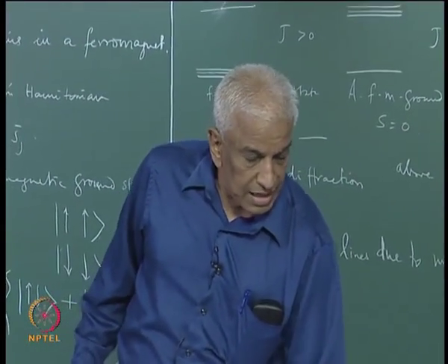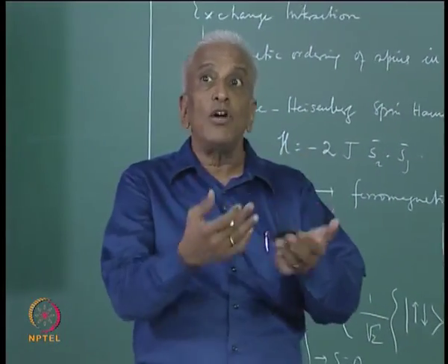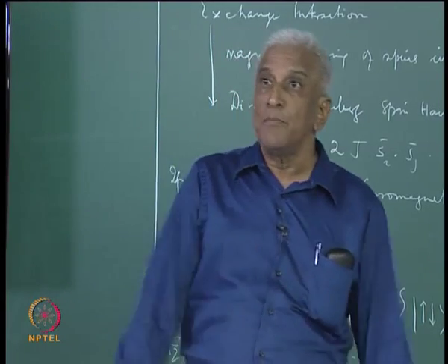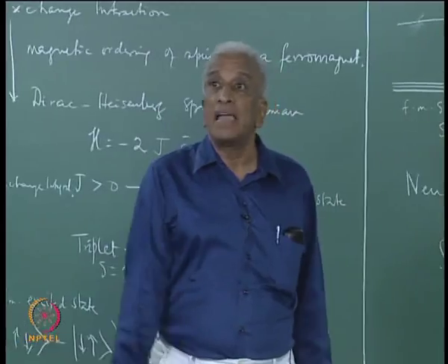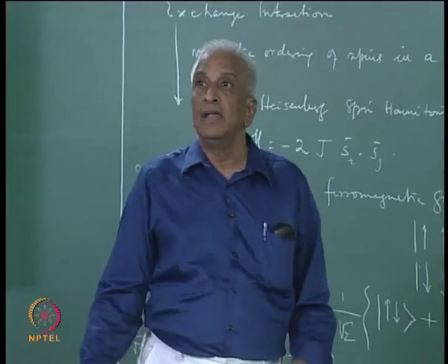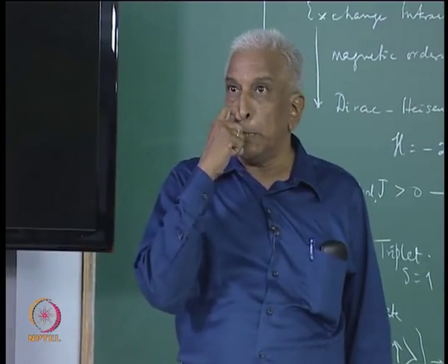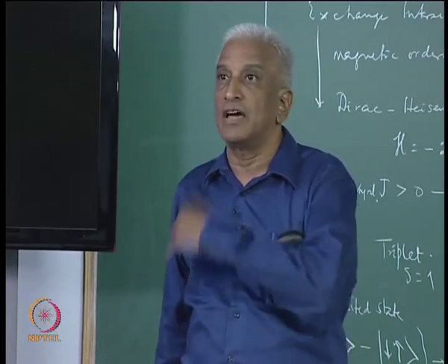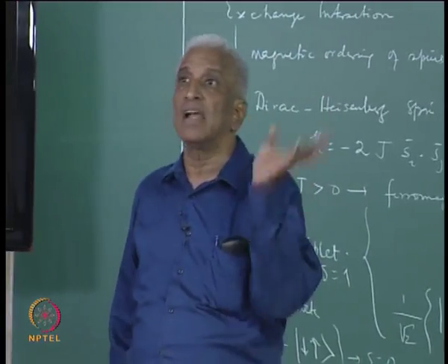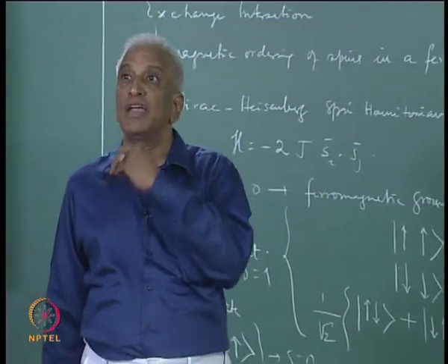Therefore, one can easily distinguish the onset of magnetic ordering, antiferromagnetic ordering in particular, at the Néel temperature by the appearance of these magnetic superlattice lines. The positions of the superlattice lines are indexed just the way the X-ray diffraction lines are indexed, according to the plane from which they are reflected, and that is the position. Then the next information is their relative intensities, which tells us about the nature, the kind of ordering pattern present.